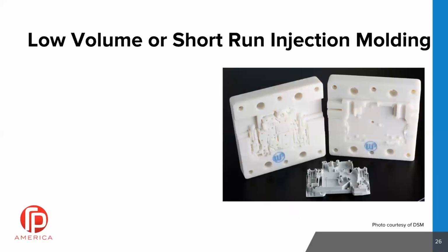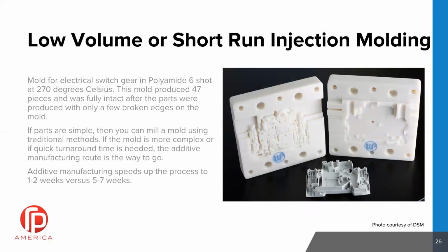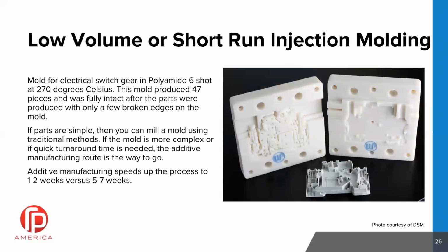Another great opportunity for this material is in low volume or short run injection molding inserts. I've been pushing this a little bit. I may have even talked to some of you out there regarding this, but this is a great example. This is a mold for a switch. It's a polyamide 6, and it was shot at 270 degrees Celsius. And this mold was able to produce 47 pieces and was fully intact with only just a couple of small little edges breaking off after that many shots.